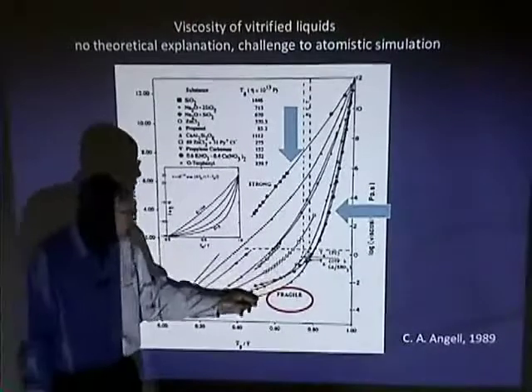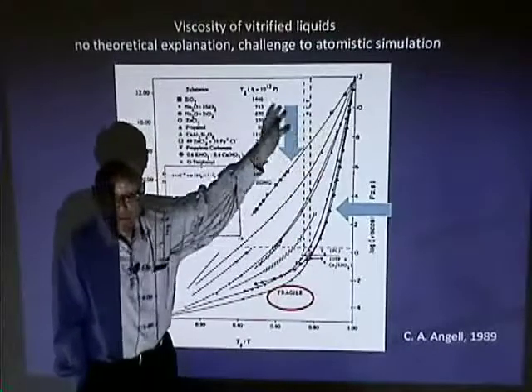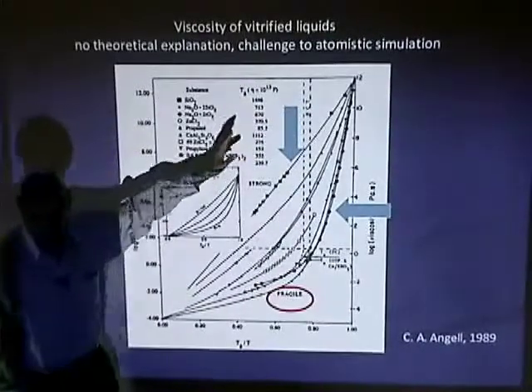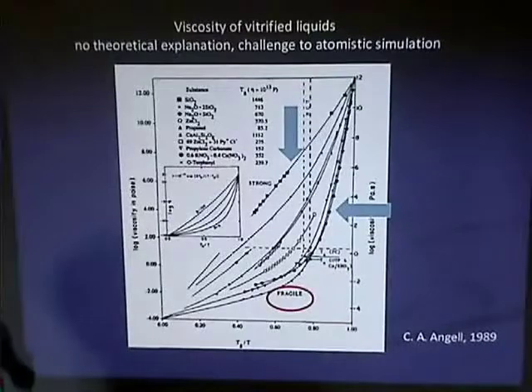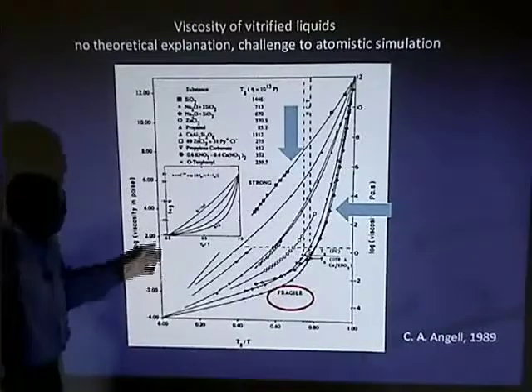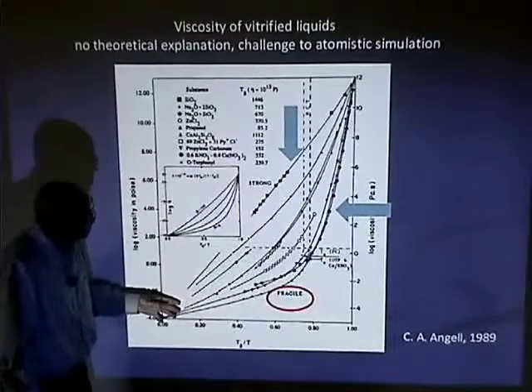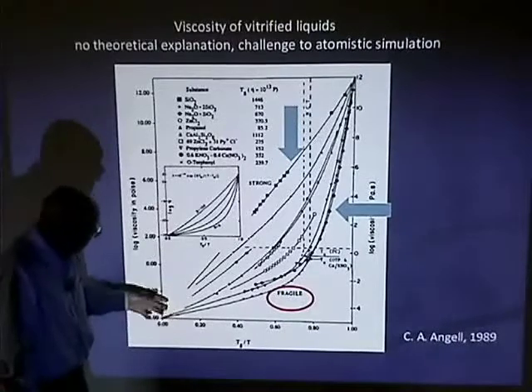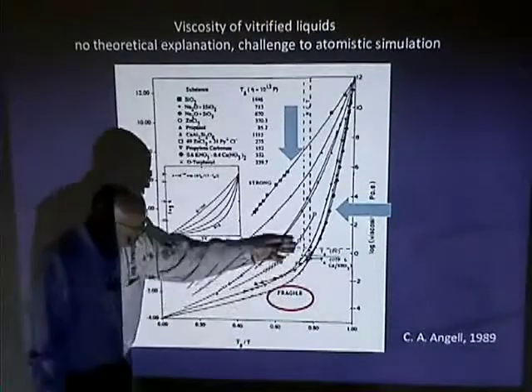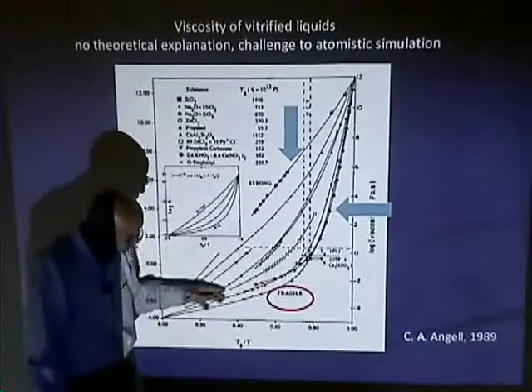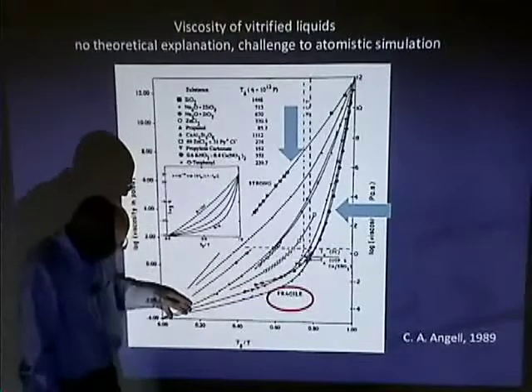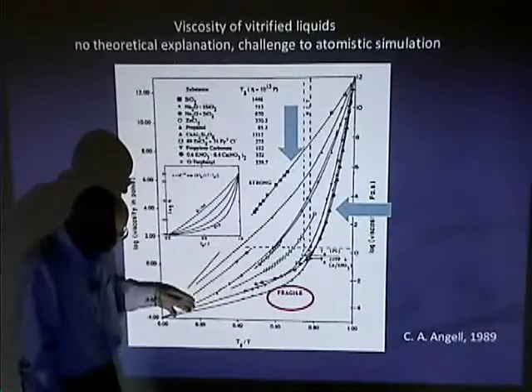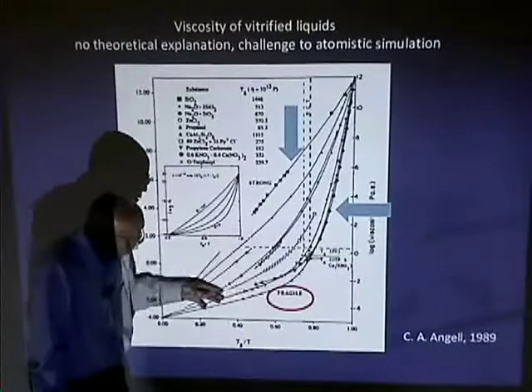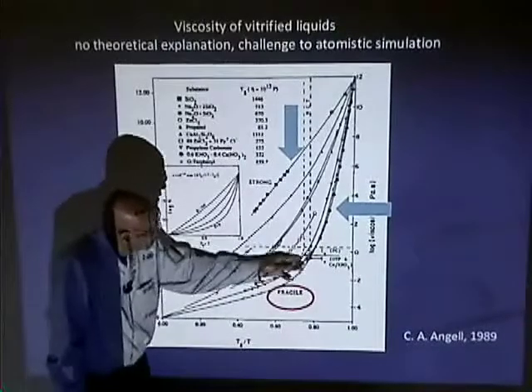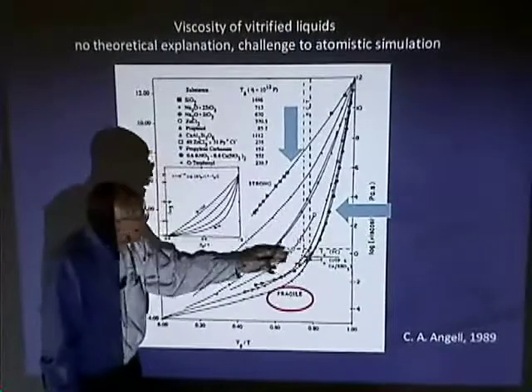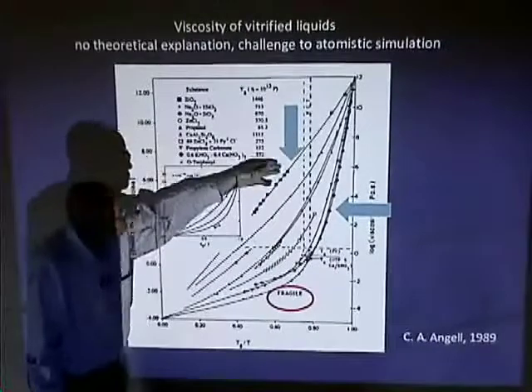And then it runs into a regime where the activation barrier is highly temperature dependent. Some people think there may be another transition further up, but we don't have to talk about that. So the data suggests you have liquids that behave with very severe, monotonic simple behavior, and this is also monotonic but rapidly changing. Then you have something that doesn't seem to show much change at all.